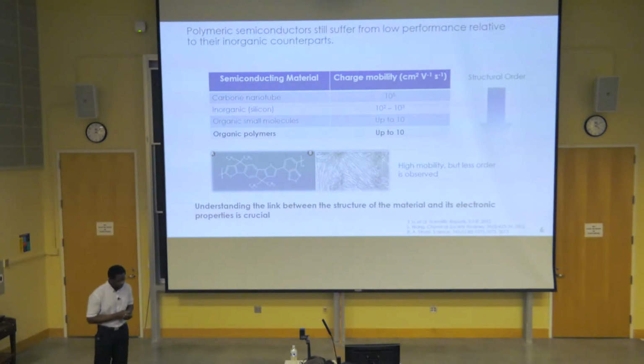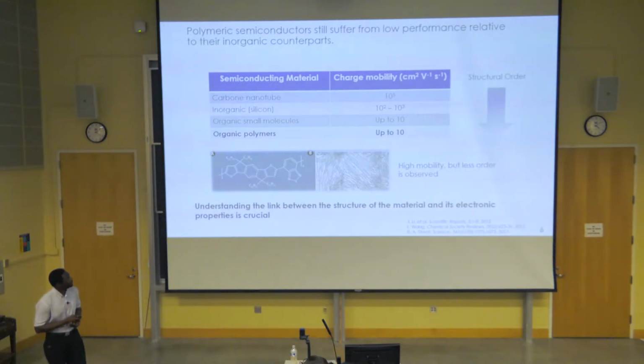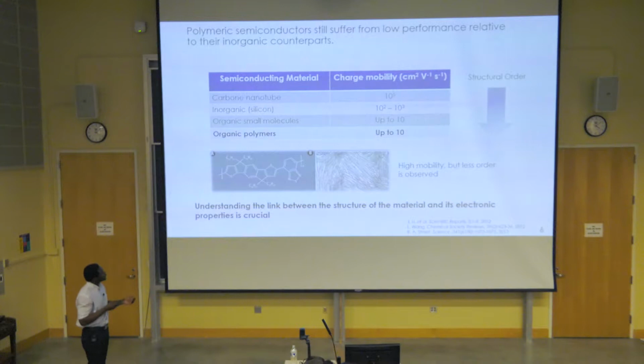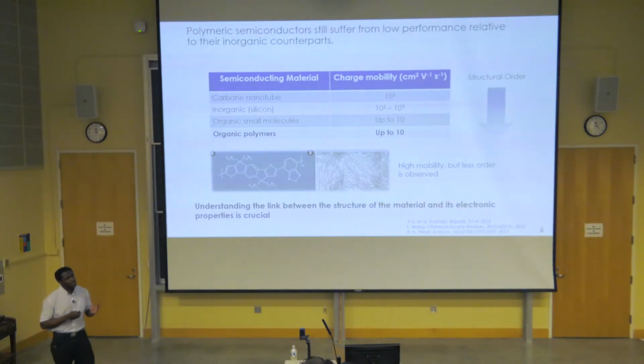Unfortunately, semiconducting polymers are known to have a very low charge mobility compared to their inorganic counterparts or compared to other materials. And this is due to the fact that within this material, charges are highly localized. It happens that the trend in this table here correlates with the structural ordering of the material. And for a long time in this field, people have tried to increase the charge mobility of these materials by increasing the structural order of the material.